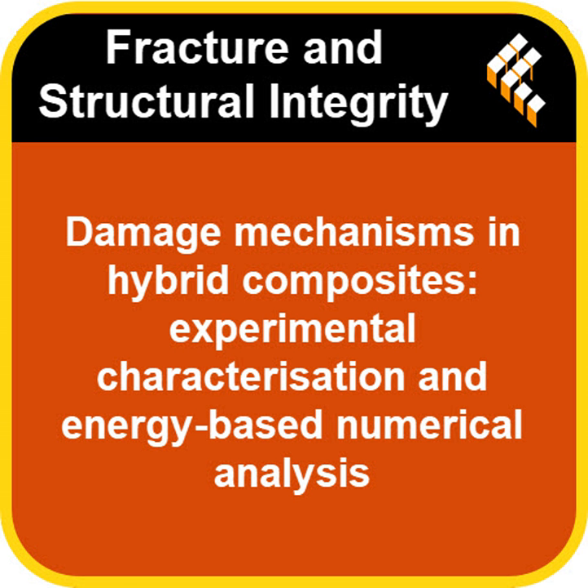Right, compression. In the 2G6C sample, glass on tension, the squishing damage started in the glass layer itself, layer #1, and then spread to the carbon layer right next to it, layer #2. So starting in the glass. Yes. But in the 6C2G sample, glass on compression, it started in the second glass layer, layer #2, then jumped to the first carbon layer, #3, and then spread to the carbon layers below, #4.